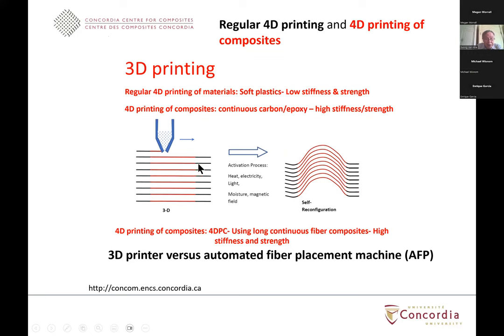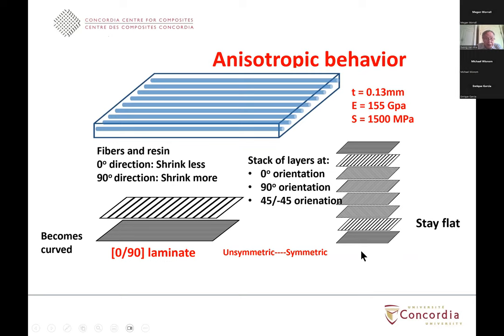So when you subject it to some kind of activation process, such as heat, electricity, light, and so on, this flat structure changes to a curved structure. So basically you lay down something on the flat mold, and then you activate that, and you have a curved structure. And the fourth dimension is the change of the configuration from flat to curved. So basically here, the 3D printer we use in this case is the automated fiber placement machine. And the principle behind this is that we use unsymmetric laminate. I think most of the time people in the aerospace industry use symmetric laminates, which is good. Except in the case of 4D printing, we use unsymmetric laminate that is 0-90.